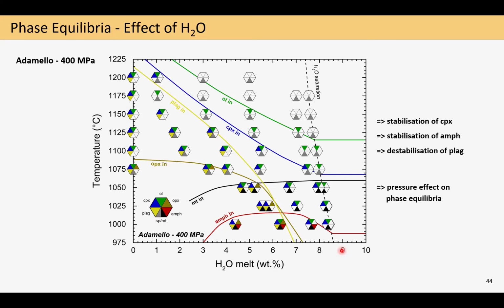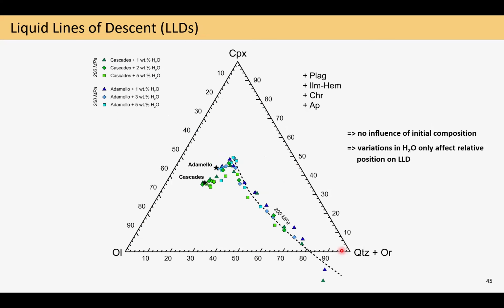And this all then can, of course, also be translated into the liquid line of descent, so the chemical evolution trend of the residual liquids. Here first only shown in green for the Cascades at 200 megapascal and the Adamello composition at the same pressure, where interestingly we cannot really see a distinct influence of the starting material composition on the liquid line of descent. So they both define one single trajectory, and moreover, it's also interesting to see that variations in bulk water contents seem not to affect the LLD itself. So they're all lying still on the same trajectory.